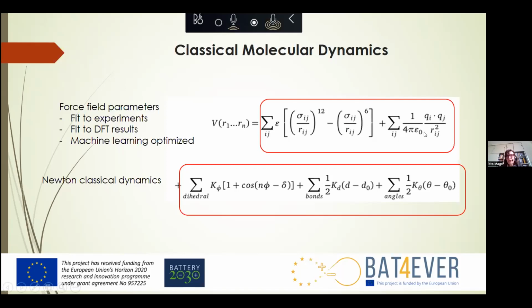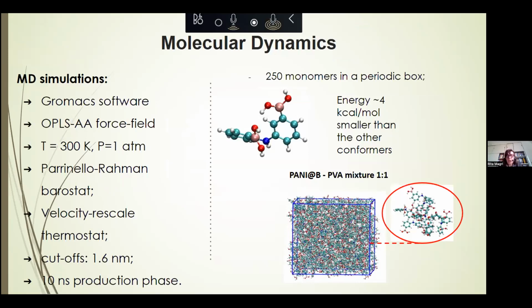so electrostatic and Lennard-Jones potential. And then we have some bonding parts of the potential to describe the energy contribution of bonds, of the angles, and the dihedral arrangements. And from this potential, we obtain the forces, and the system moves following Newtonian classical dynamics. And again, we have done molecular dynamics simulations here for many systems, ionic liquids, and so on. But here I present results for the self-healing polymers. And again, boronic doped polyaniline and PVA.